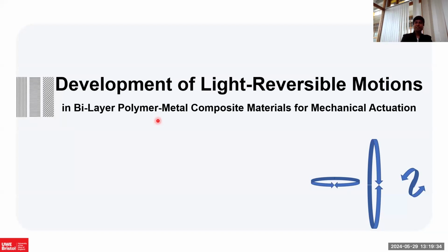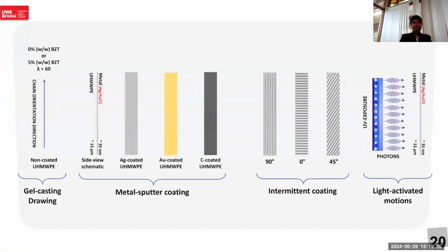It is the development of light reversible motions in bilayer polymer metal composites. Since we found that as we go towards the film thickness, we have a thermal gradient, the light is either not being used or is passing through the material without being used. So from that, we thought that we have to create a barrier at the later end of the film using a fully reflective material, maybe like silver, or a reflective material which can half absorb and half reflect the light, such as gold, and also a fully absorbing material such as carbon.